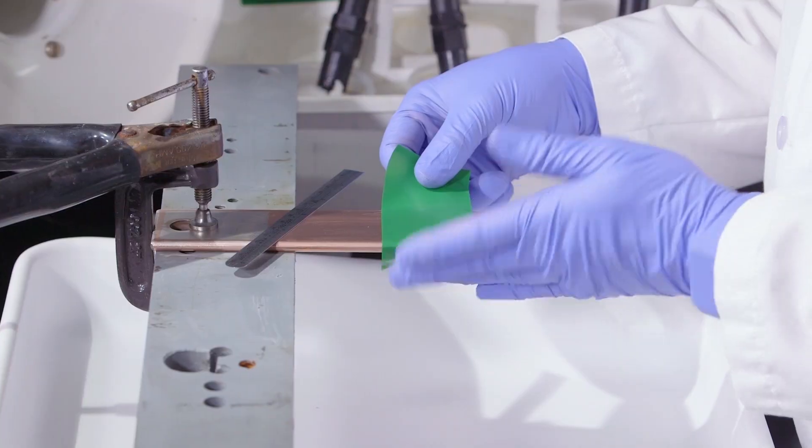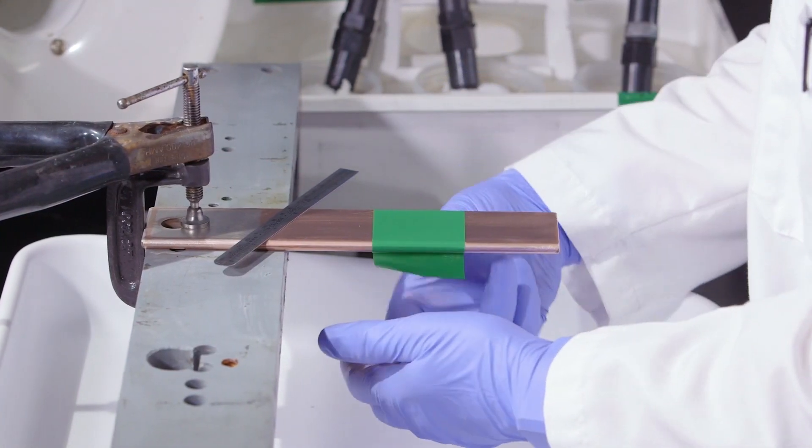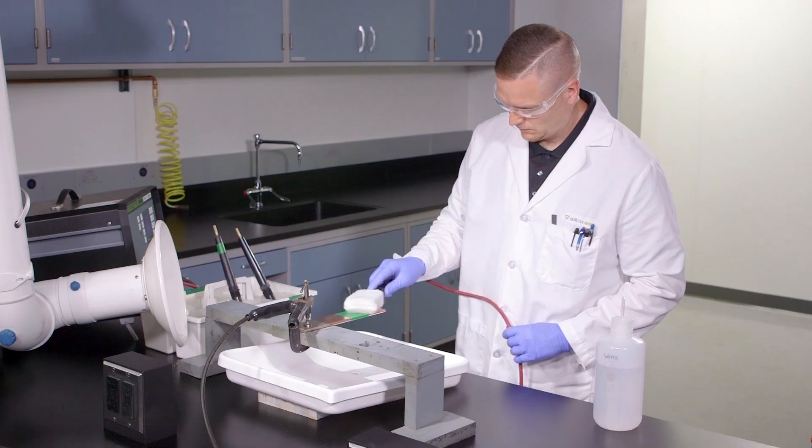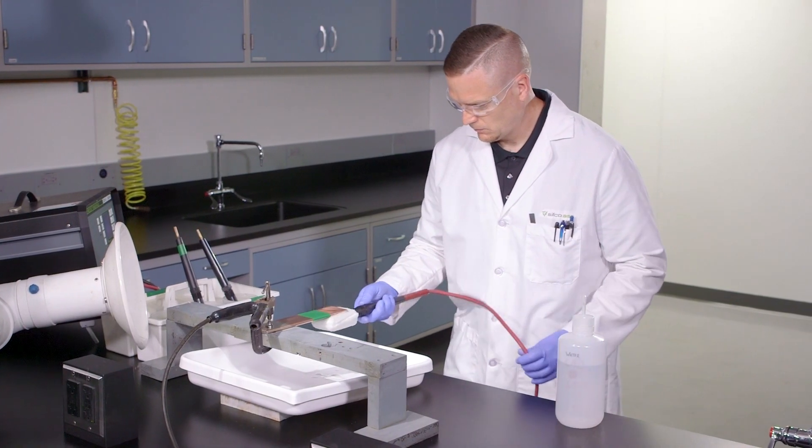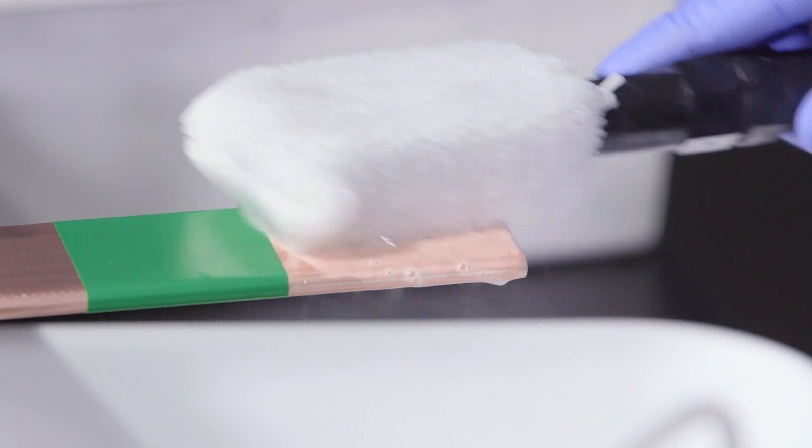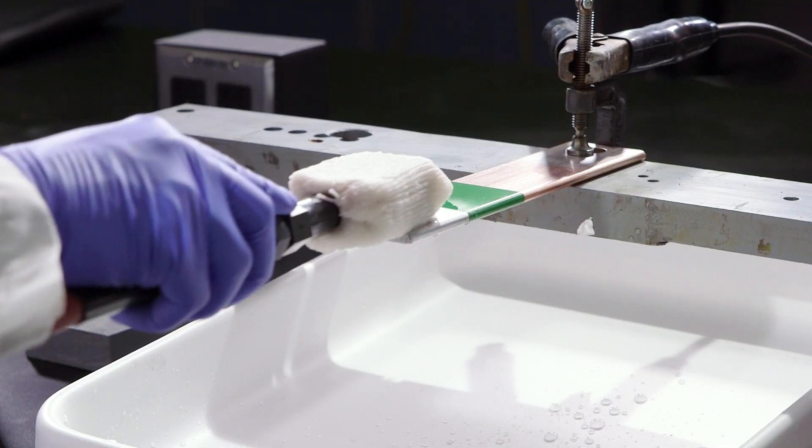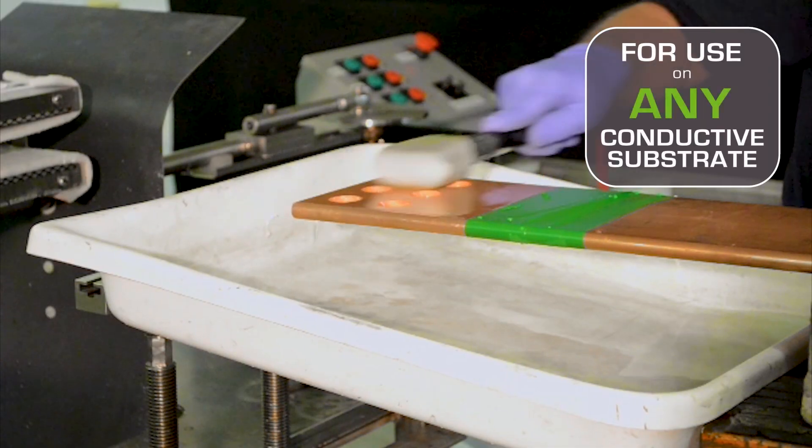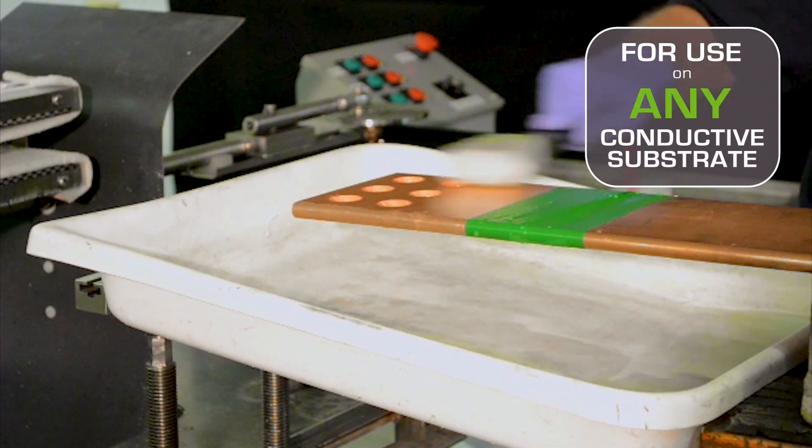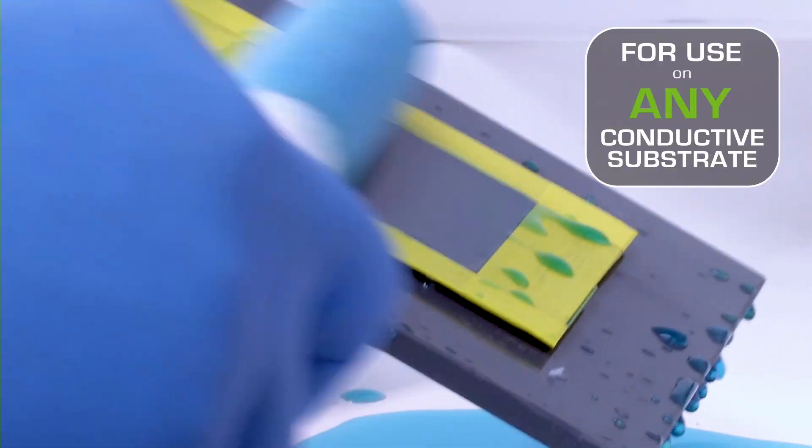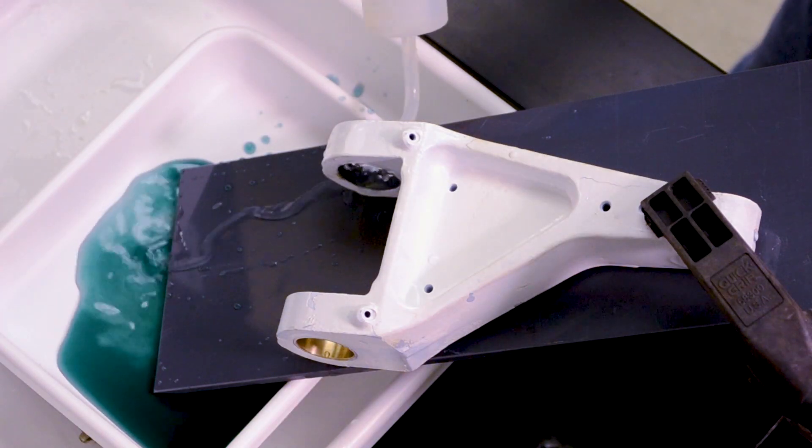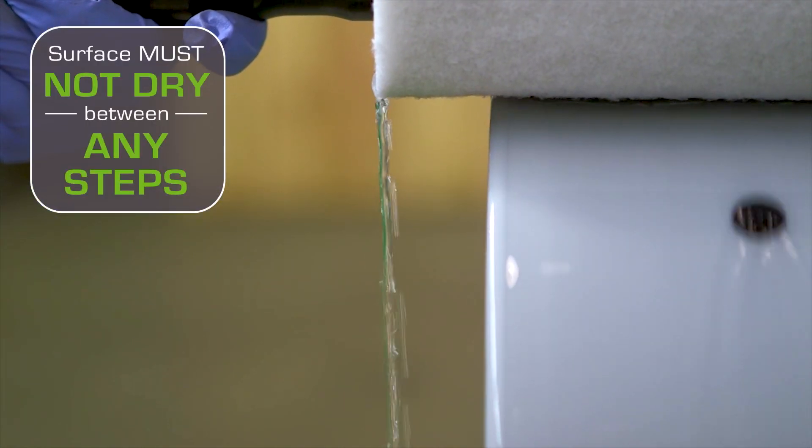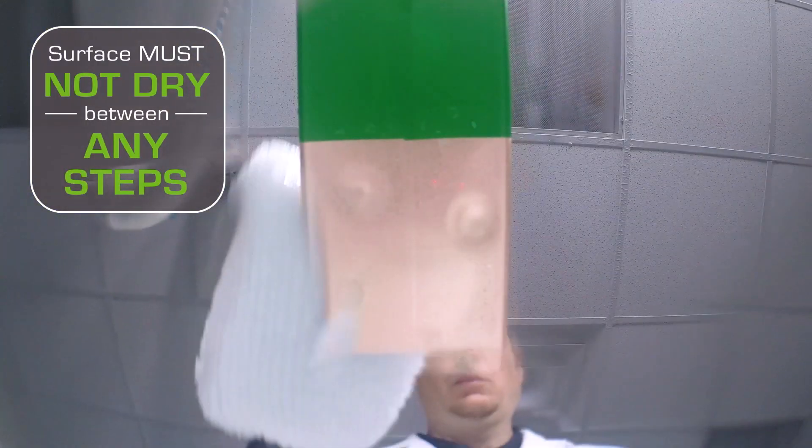The SIFCO process is simple to perform. In a typical operation, the select area of a part is first masked, then a series of preparatory steps are conducted to ensure an adherent deposit. The last step involves plating the metal deposit to the desired thickness. The preparatory steps depend on the base material and not the plating solution. Selective plating is a continuous multi-stage process in which the surface must not be allowed to dry between any preparatory or plating steps.